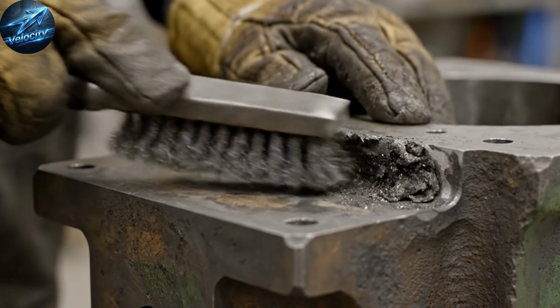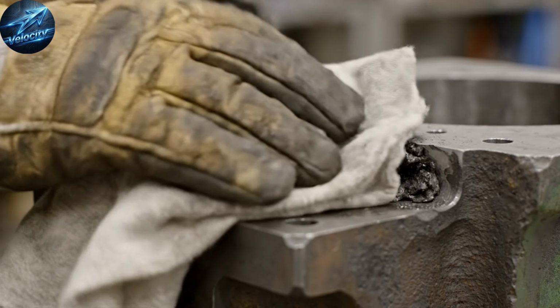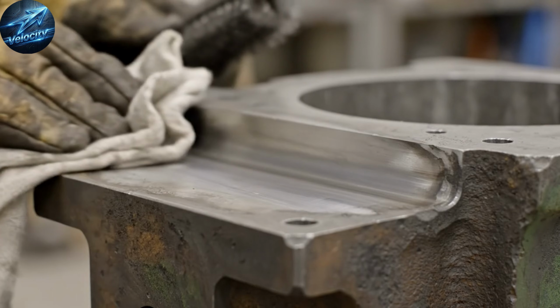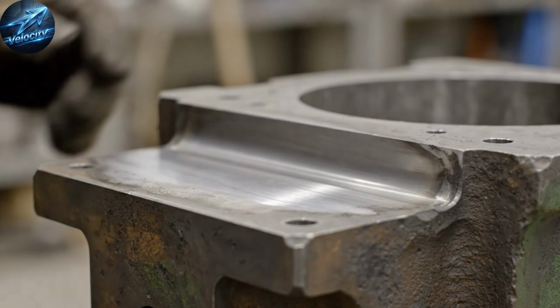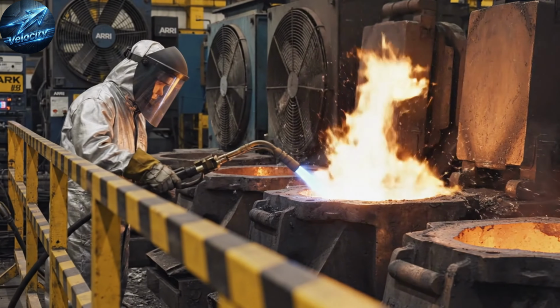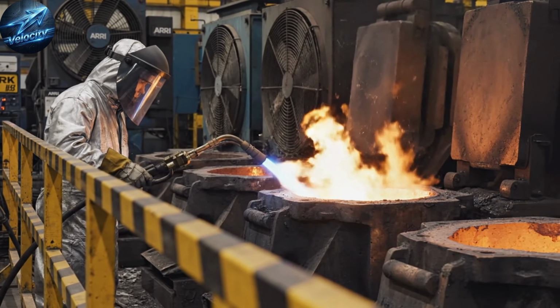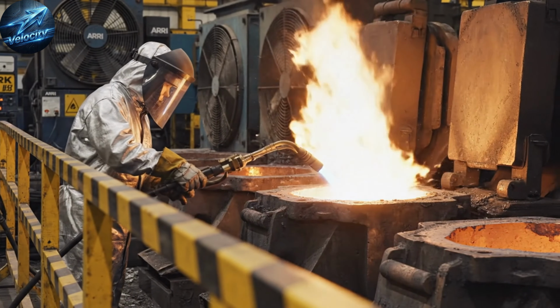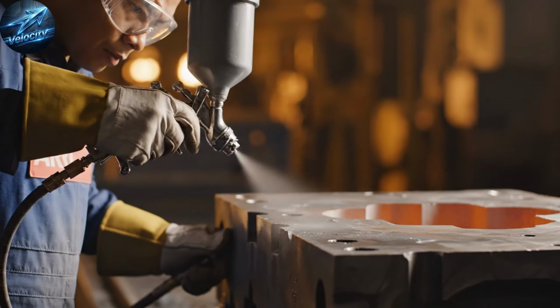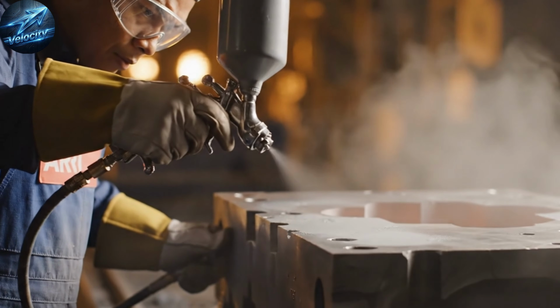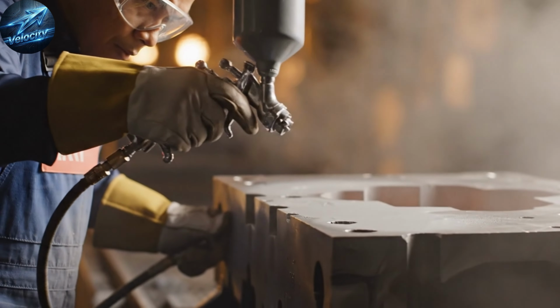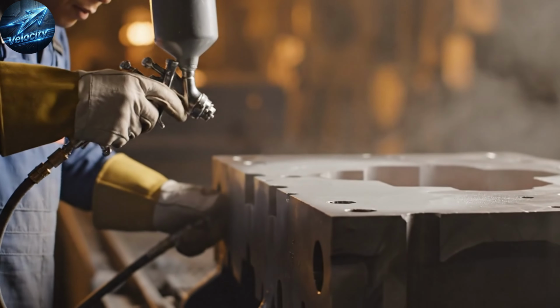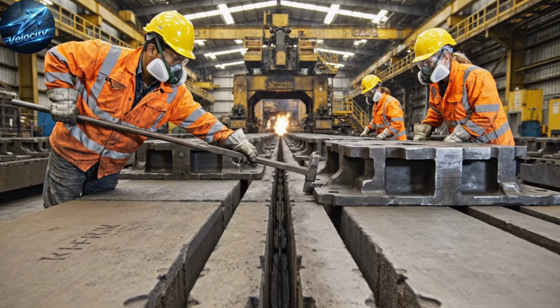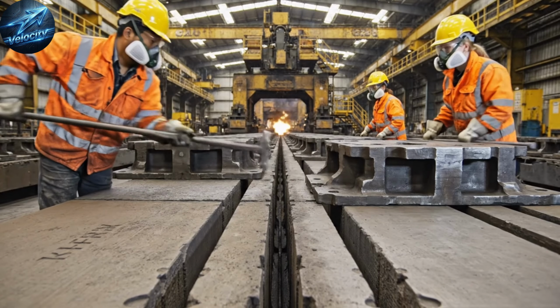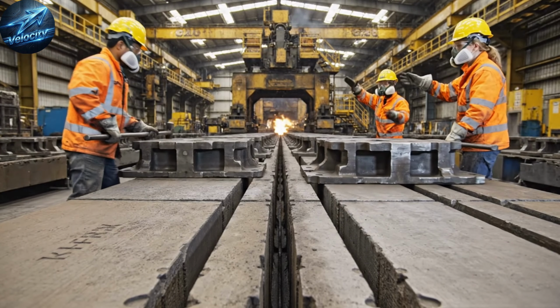Molten metal meets water and it doesn't sizzle. It explodes. That's why the casting floor must be dry, molds must be clean, preheated, coated, numbered for traceability. Pour too slow or stop-start and you create cold shuts, weak layers inside the ingot. They pour a small primer, stabilize flow, top up for shrinkage, and cool under control. Then stamp the ingot with batch identity, no hiding.